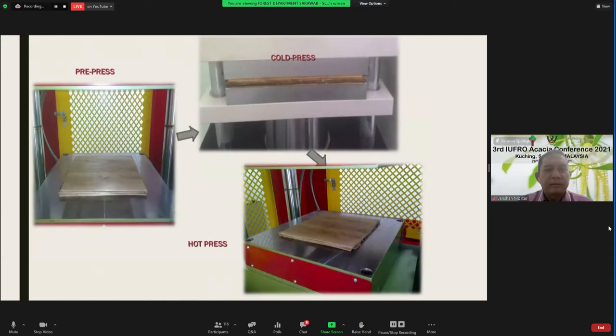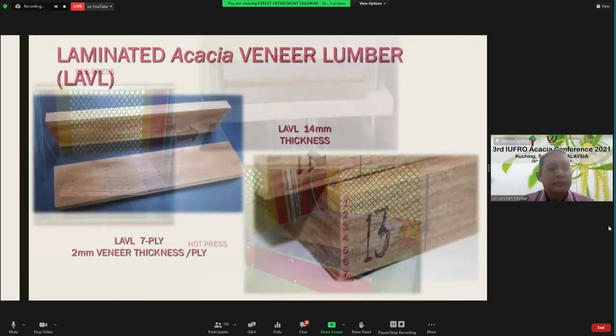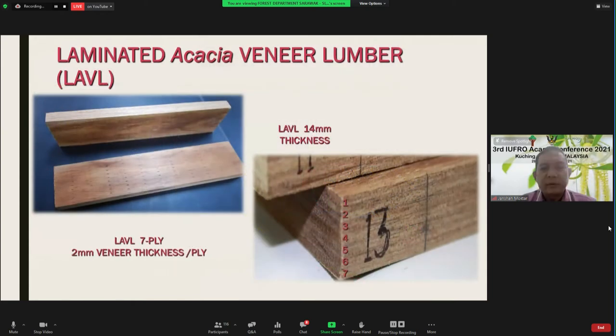This is the fabrication process for the LVL sample: from the pre-press, then cold press for 20 minutes, and finally hot press for 6 minutes. This is the final sample for laminated Acacia veneer lumber. This one is for 7 ply.